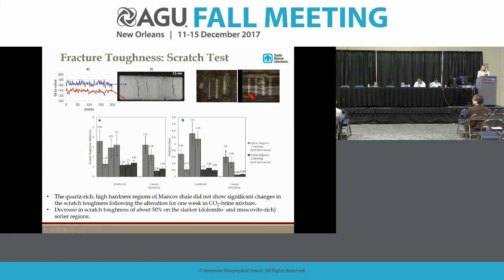And here's just a photograph of different scratches. And again, as I mentioned before, we can see a difference between scratch depth on different layers, but it's hard to characterize. So actually, these results are from scratches that were imposed this way, along the lamina. We probe every lamina separately. And so these bar charts here illustrate our results.